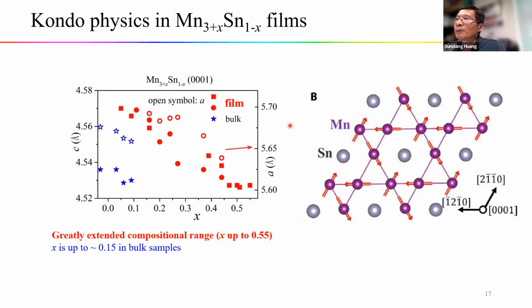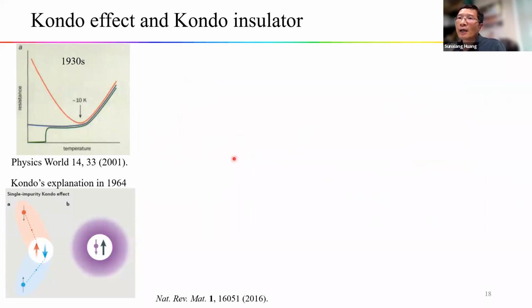Before I discuss the transport property, let me briefly discuss the classical correlation effect, which is the Kondo effect. The Kondo effect was observed experimentally almost 100 years ago. For a usual metal, when we decrease the temperature, the resistance will decrease and reach some residual value due to the impurity scattering. But for some material systems, people observed the resistance reaches some minimum value at a certain temperature, after that, the resistance actually increases. That troubled physicists for about 30 years, until Kondo gave an explanation.